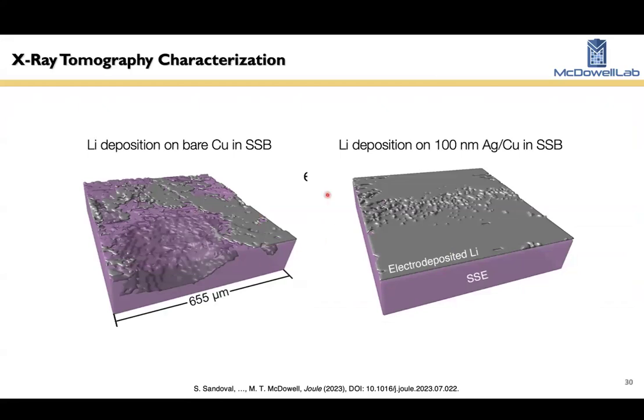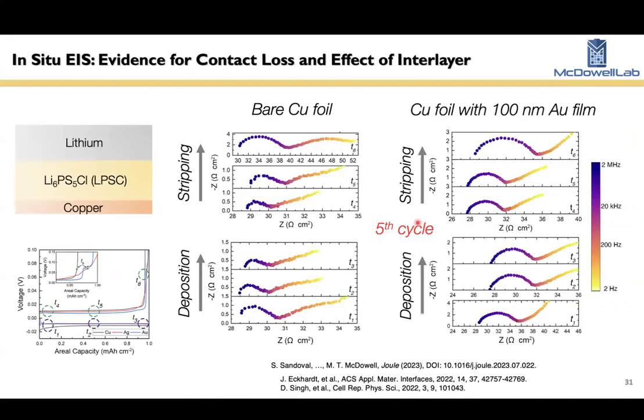So these are just some X-ray characterization now showing, just like the FIB, we see that when we have silver present, the deposited lithium is much more uniform in thickness across the interface. Okay, so why is this happening? Well, actually, before I get there, this is one more piece of evidence,